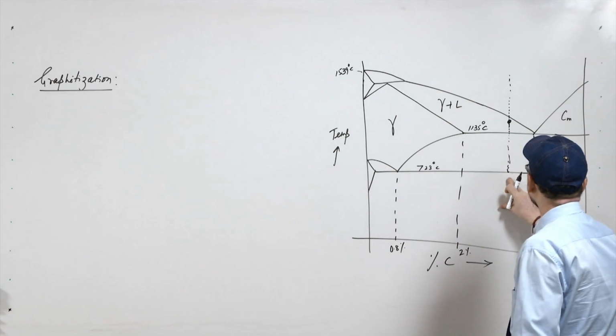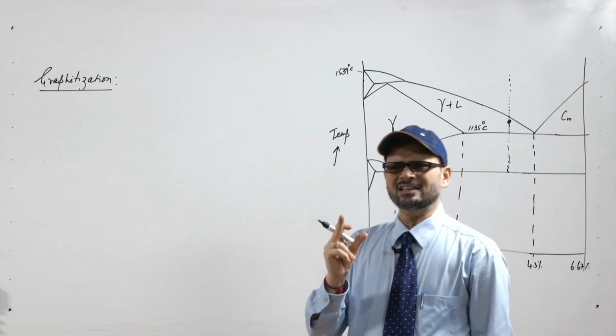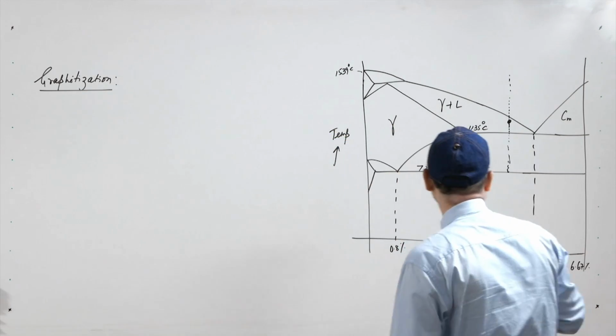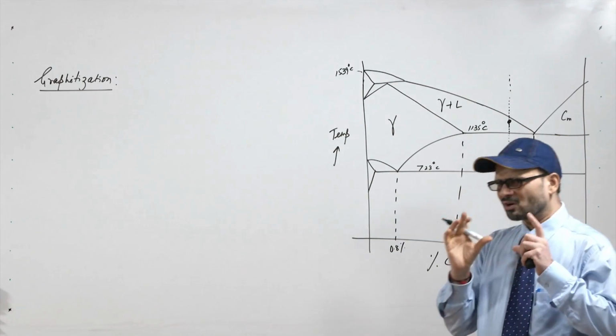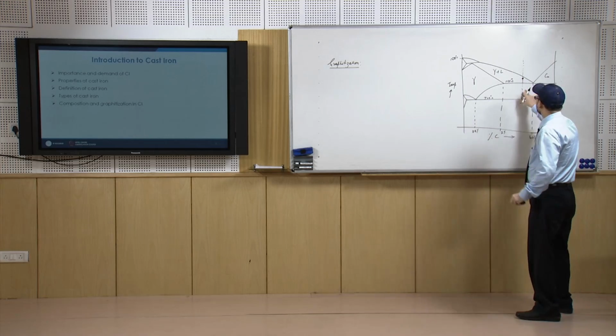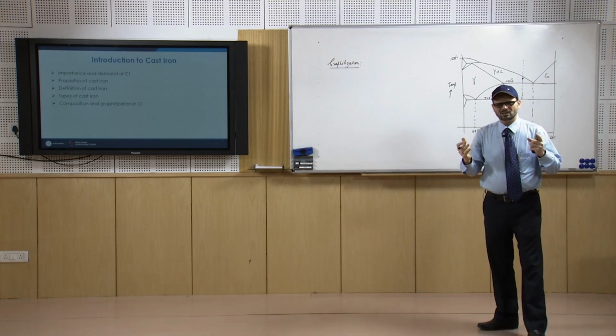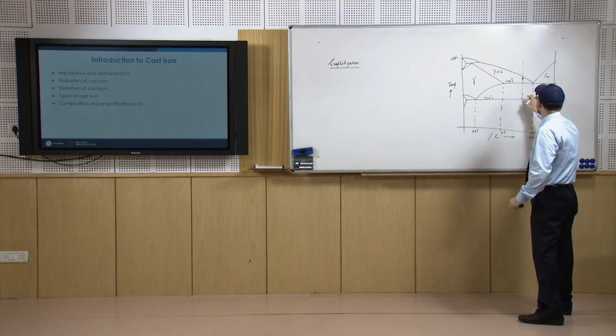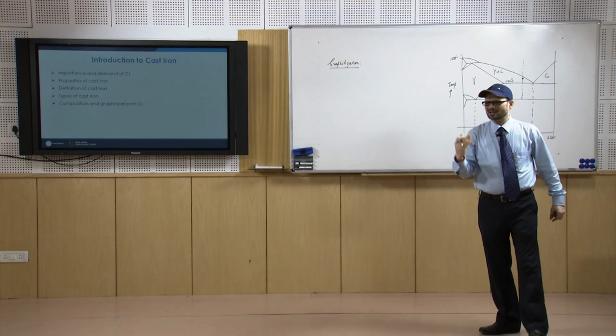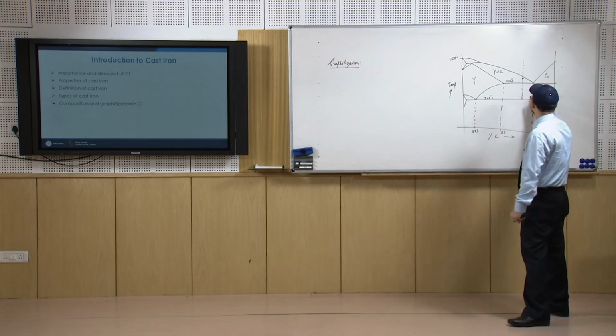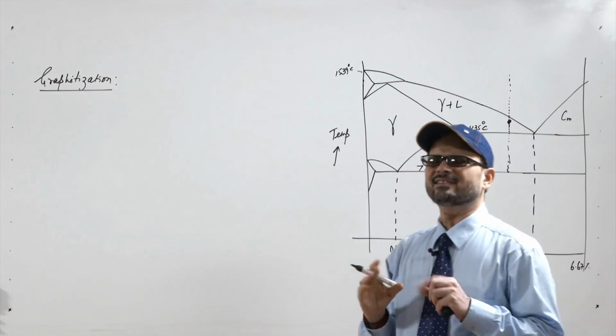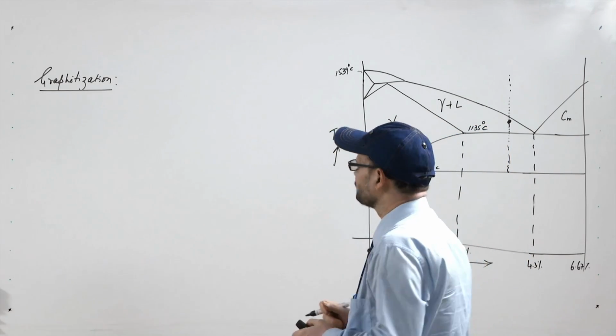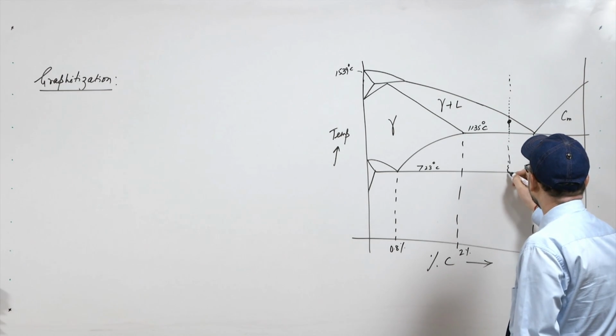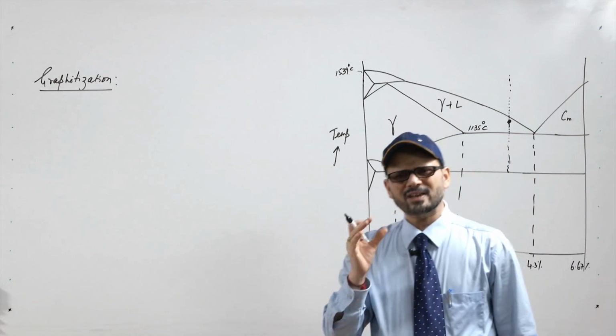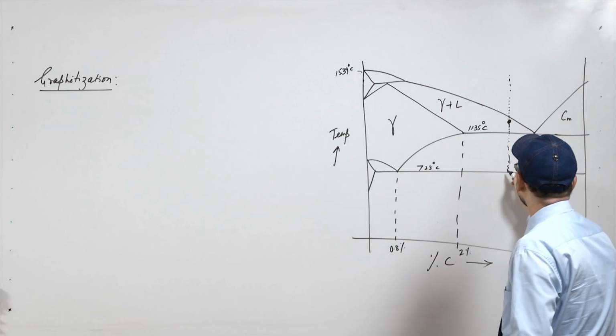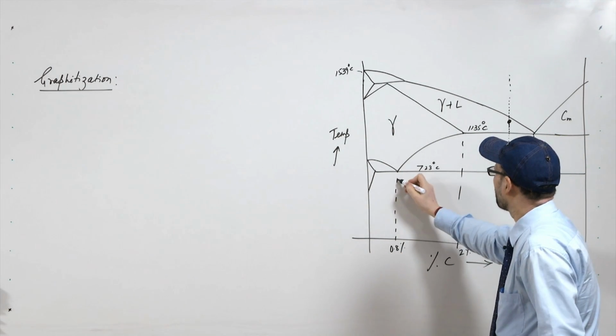Now, the chief role of this alloying element silicon is that silicon is a graphitizer. Because of the presence of silicon and also because of the low cooling rate, this carbon is basically present as the graphite. Graphite is soft, and that is why in the cast iron, as you cast in normal circumstances, if you have enough silicon and the cooling rate is moderate, you get the carbon in graphite form. Once it further comes down, after this line, you have this composition, this is your eutectoid.